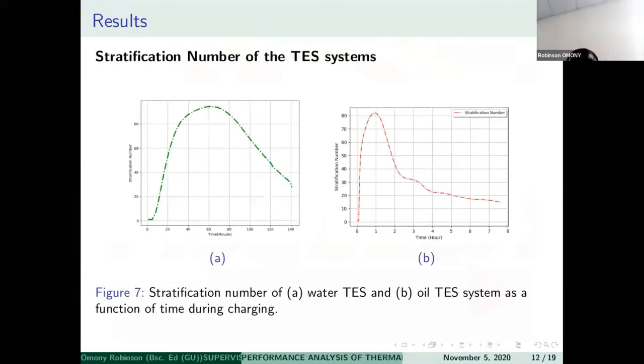Then stratification was used as a measure to define how efficient this system is in energy storage. So a high stratification number is an indication of a high charging energy and of course charging exergy. So the water test system achieved a high stratification number of about 86. But when you compare to that of oil, it attained a stratification number of 82, and correspondingly charging energy were also achieved. Maximum charging energy were achieved at these high points of stratification number.